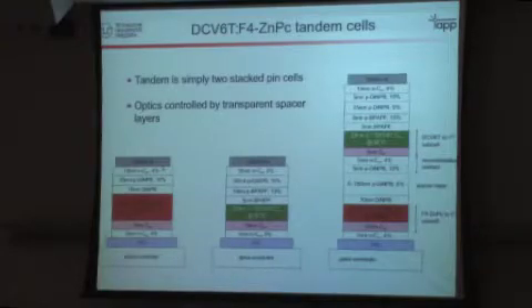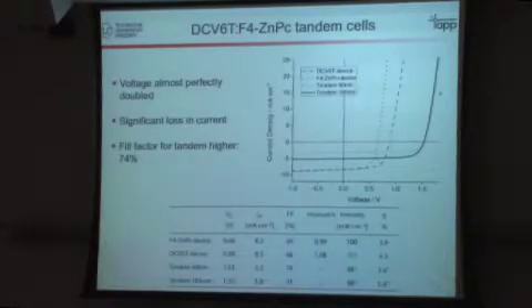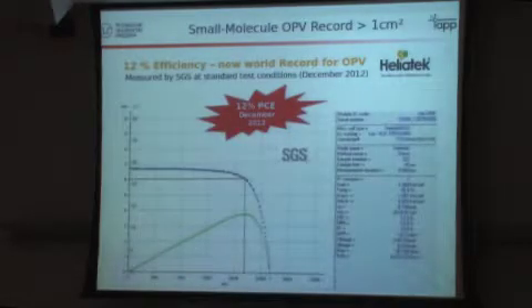What you see here now is that these devices are fairly complicated. You have something like 10 or 12 layers, but using this vacuum technology, this is not difficult to do. And you can nicely double the voltage. You get very high fill factors, higher than for the individual cells. What we didn't really achieve in this case was good current matching because of the spectral properties of the two materials. And working together with Heliatek, we optimized that step by step,